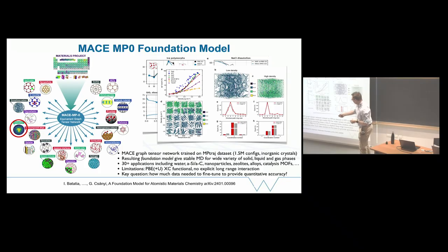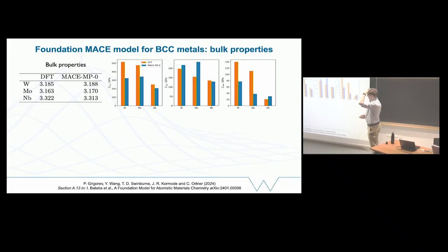So of the 40 applications, this is the little one over here that I was involved in. We first took the model and tried it out on the kinds of things I've been showing you until now. So looking at dislocations in tungsten as a simple case, looking at lattice constants for tungsten, molybdenum, and niobium. They're not bad. It's a bit soft generally. So these are the C11, C12, C44 elastic constants. I wouldn't say this was predictive accuracy. I wouldn't use this to do science with straight away, but it works and it does something and it's quick and easy to try.